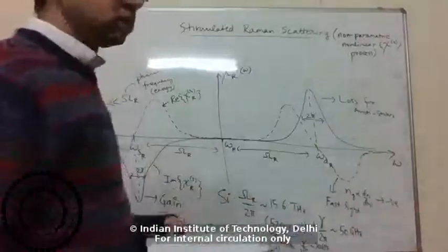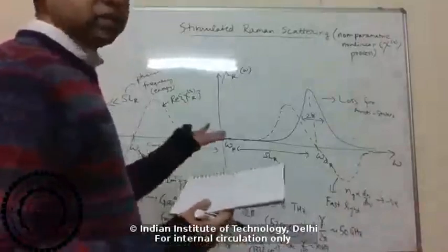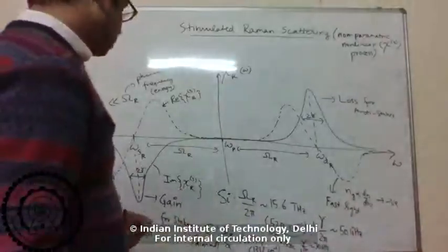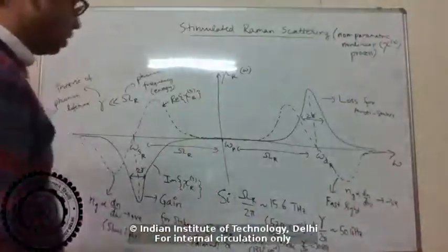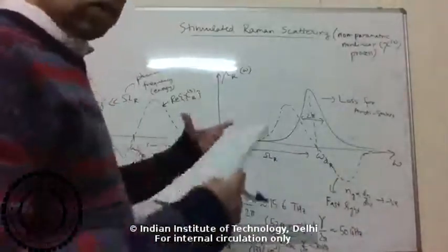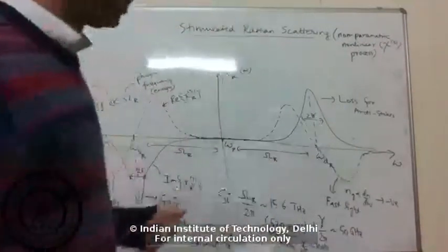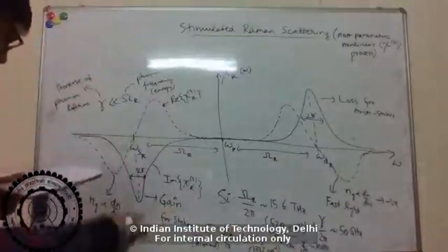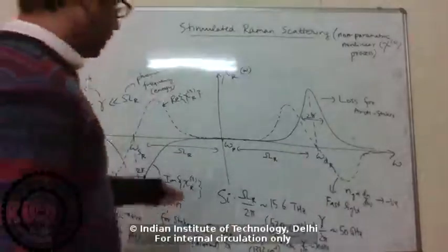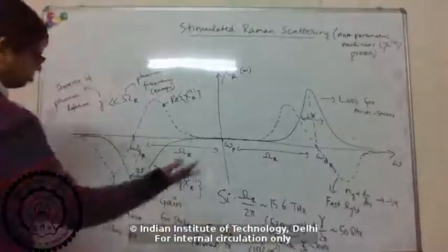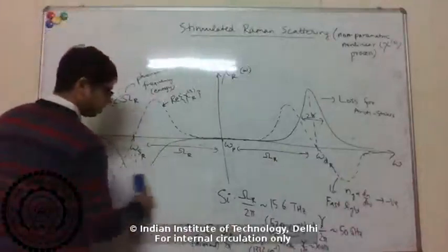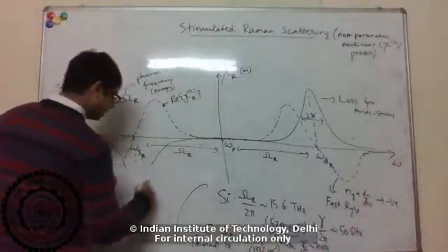Because the material is very ordered and nice, the phonon lives for a long time, and because the atoms are all bonded close together covalently, the vibration also happens at a high frequency. So we can contrast this with an amorphous material like glass, silica. Right? So these are crystalline materials.